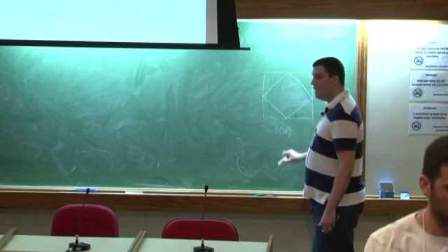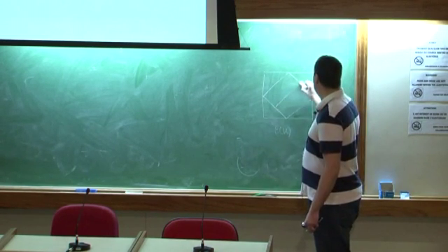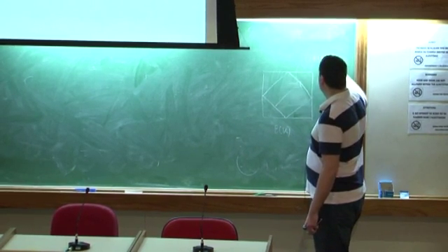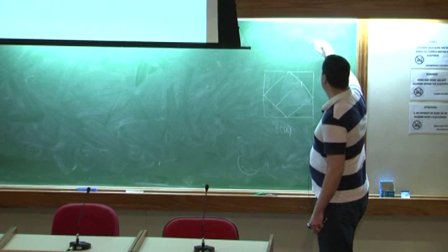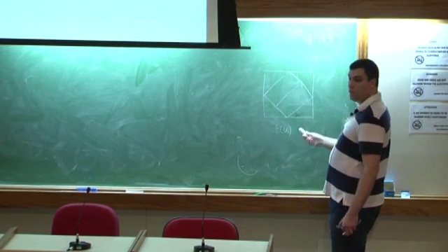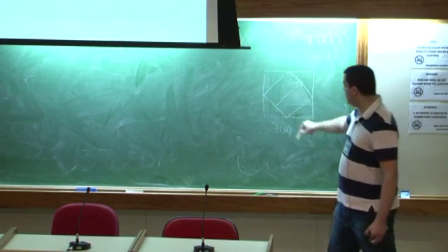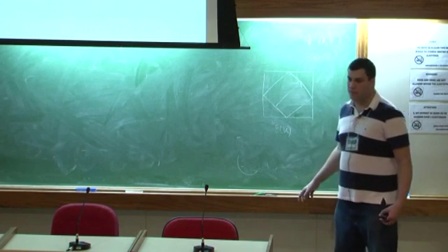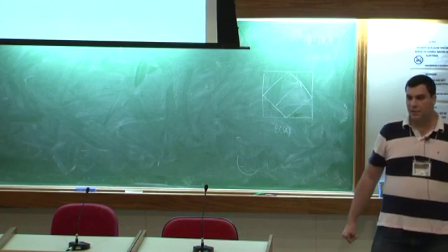Now, if you take the energy at momentum k, and you want to compare it with the energy at momentum k plus q, and my q here is (pi, pi), you find that one is minus the other, meaning that these parts of the Fermi surface are parallel. This is what's called nesting. That's where the name nesting comes from, I assume.